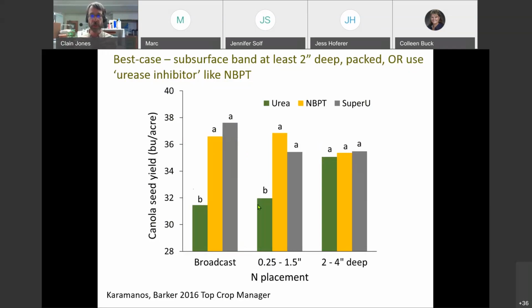The other products slowed the amount of volatilization. When that nitrogen was put 1/4 inch to 1.5 inches down, the benefit of these urease inhibitors was somewhat less, but really it didn't equal out until the nitrogen was placed 2 to 4 inches deep. So what that tells me is below 2 inches deep, urea must not volatilize, because it did no worse or no better than the NBPT or the Super U product, which also has NBPT in it. So that gives you two options as producers. One would be to use a protected product if you don't want to lose 4 or 5 bushels per acre of yield, or bury your nitrogen subsurface, band it at least 2 inches deep. And then it doesn't matter what product you use, you might as well use urea because it's less costly.